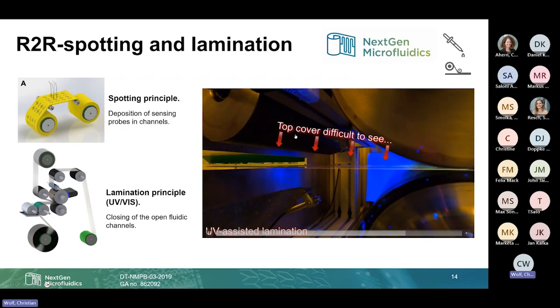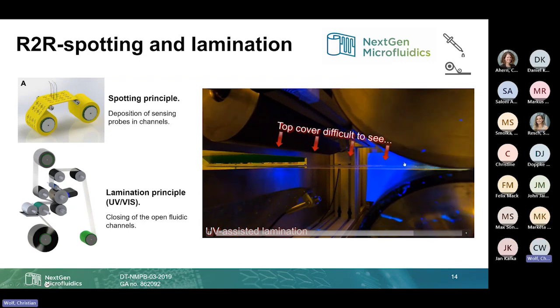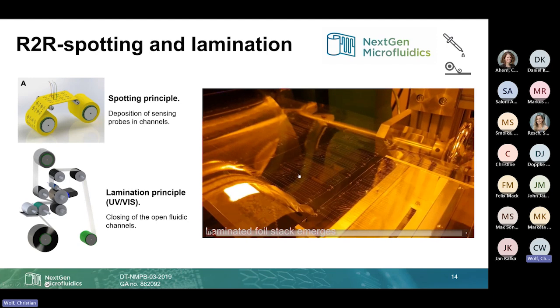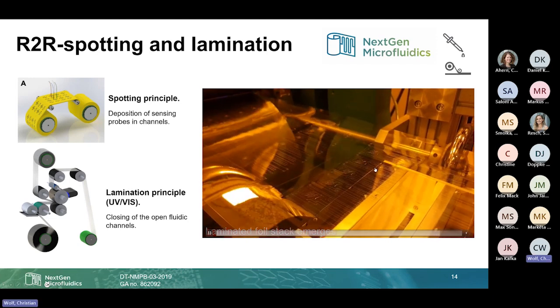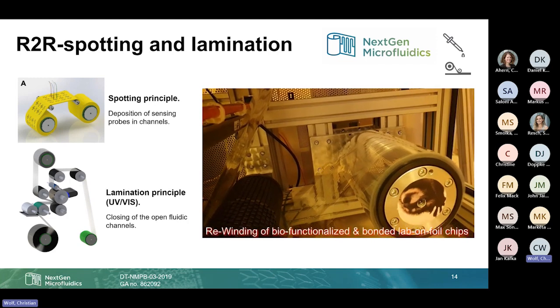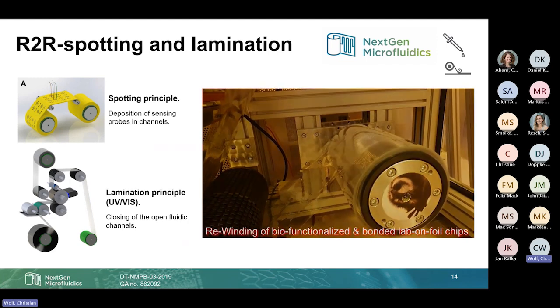So maybe it's a little bit hard to see. That's the cover foil, and that's how it is then connected with the actual chip, the imprinted and spotted chip. With the UV anneal process, imprinting process, this is done so that on the cover foil you also have a very thin layer of this cross-linkable resin, and then the imprinted chip and the cover foil are pressed together, and then you expose it with a small dosage of UV light again, and that's how a very firm bonding can be realized. This cannot be done for the extrusion coated process, of course, because there is no cross-linking UV resin involved.